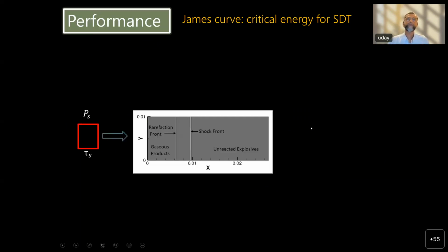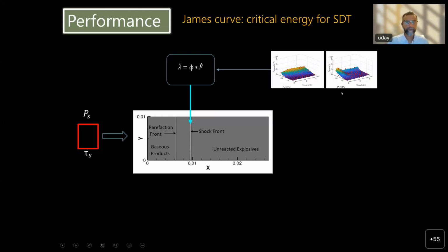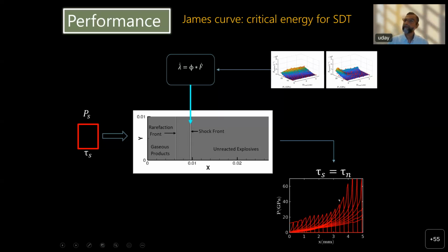Okay, so using that information from the surrogates, we evaluate the performance, and that is done as follows. We do, in a coupon, one-dimensional calculations of shock propagation of a particular pressure and pulse width. Once we propagate the shock through the homogenized macro scale material, we need this information of the lambda dot ignition and growth, just like in any ignition and growth model, and we get that from the hypersurfaces. For a particular point, if we know the pressure there, and we know the microstructure, that is the void size and all that, we can interrogate the data from the hypersurfaces, and that gives us the heat release rate in that particular cell. We put that into the macro scale and look at what happens to the shock. If the shock rises to the von Neumann pressure, then we say, okay, that's critical. And that's how we construct this James curve.